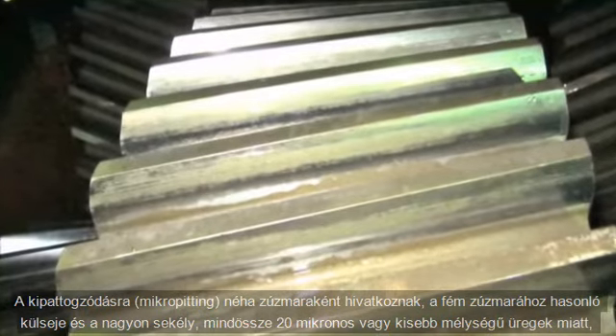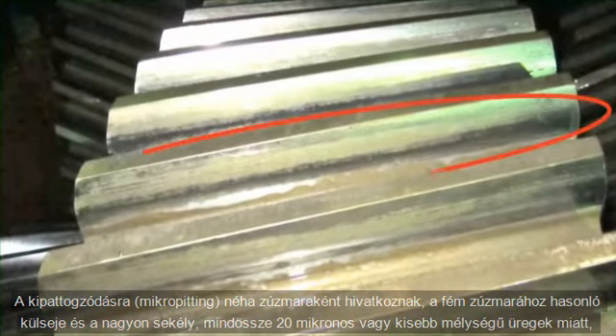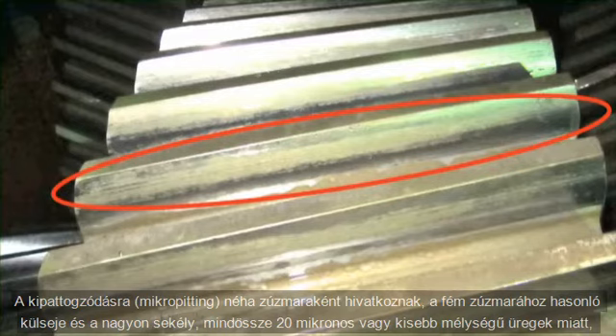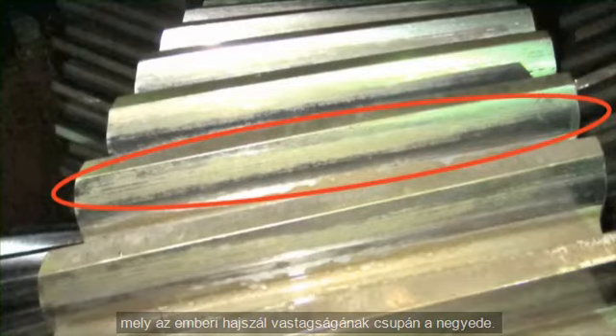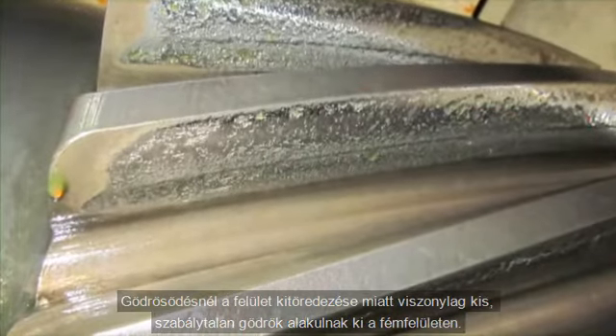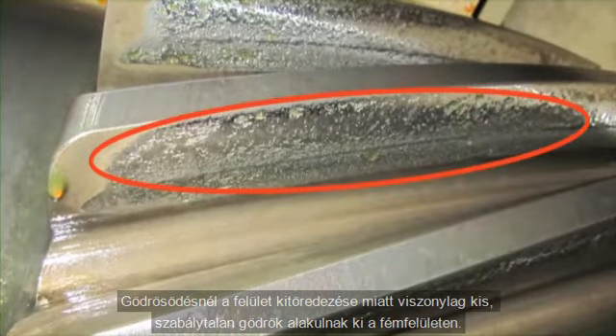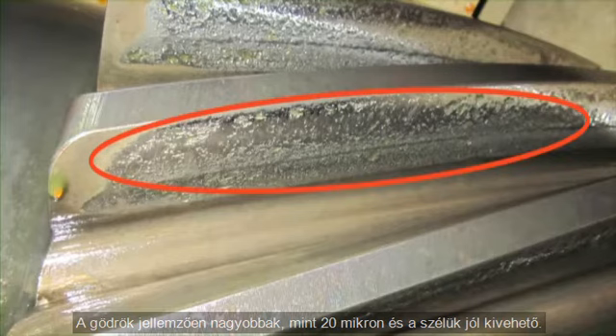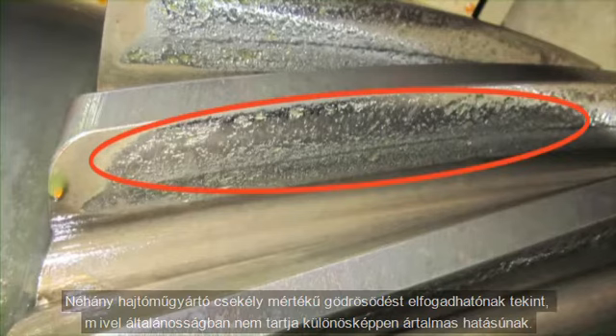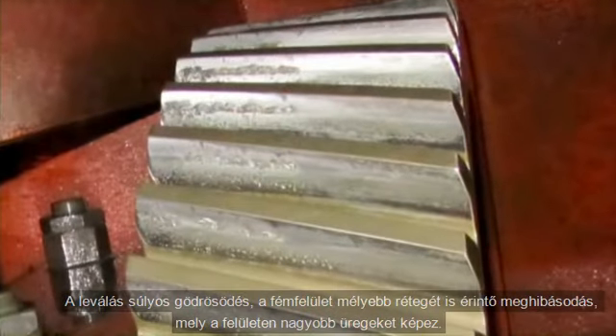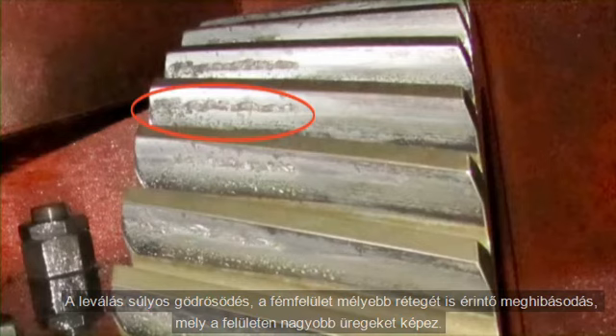Micropitting is sometimes referred to as frosting due to the frosted appearance of the metal and is characterized by very small, shallow cavities, only 20 microns or less in depth, or about 1/4 the thickness of a human hair. Pitting consists of relatively small, irregular cavities on the metal surface from the breaking away of surface material. Pits have distinct edges and are typically larger than 20 microns. Some gear manufacturers consider a minor amount of pitting acceptable, as minor pitting is not generally considered particularly destructive. Spalling is severe pitting caused by subsurface metal failure, which produces larger cavities on the surface.